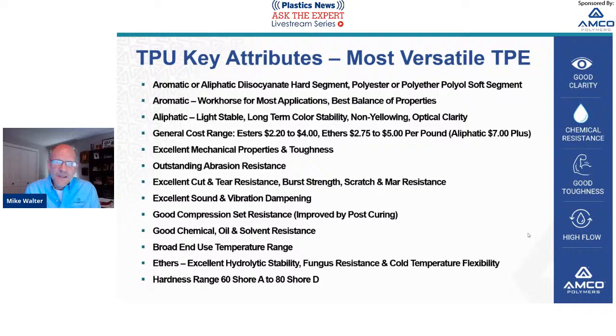The hallmark of TPU is just its excellent balance of mechanical properties and toughness. It has outstanding abrasion resistance, excellent cut and tear resistance, tremendous burst strength for pneumatic tubing, for instance, and great scratch and mar resistance. It has excellent sound and vibration dampening. It's probably the material of choice for any kind of dampening application. And along with these properties, along for the ride comes good compression set, which can be improved by post-curing, by the way, especially at high temperatures. Good chemical resistance, just an overall balance of good chemical resistance.